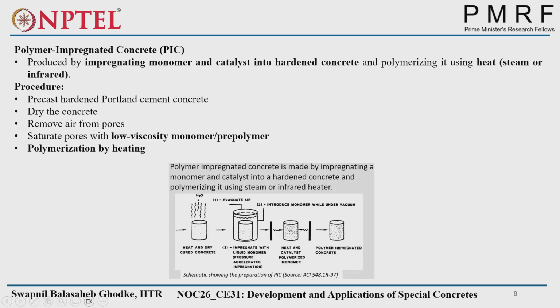So why do we have to evacuate the air, the vacuum process, while impregnating concrete? Because we need to remove all the air from the pores to fully impregnate the monomer and catalyst into the concrete. If we do not remove the air fully, we will not achieve the full potential of this concrete. And if the pores are available, we will have less durability. If any hazardous material comes into contact, it will go into those pores and affect the concrete properties. So there will be a durability effect. For that purpose, we have to remove all the air and fill all the pores with the monomer and catalyst.